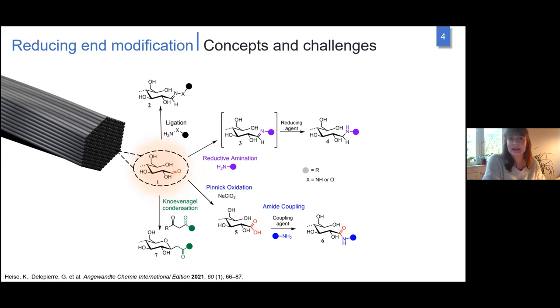All these asymmetric modifications are based on our end group aldehyde and the chemical freedom this aldehyde provides. Common reactions include ligation using oximes or hydrazine derivatives, reductive amination attaching amino functionalities, or a two-step pathway: first oxidize the reducing end to a carboxylate, then use amide coupling reactions.